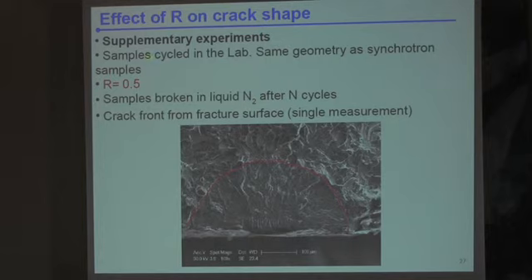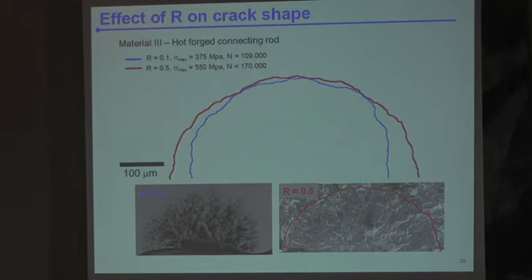So the stress ratio in that case was 0.5, and after a given number of cycles, the samples were broken open. So you can see the brittle fracture surface here, and it's not that difficult, using SEM, to find out what was the crack front at that time. And if you compare now the 0.5 with 0.1 values, you do see a difference. For 0.1, this is material number 3.